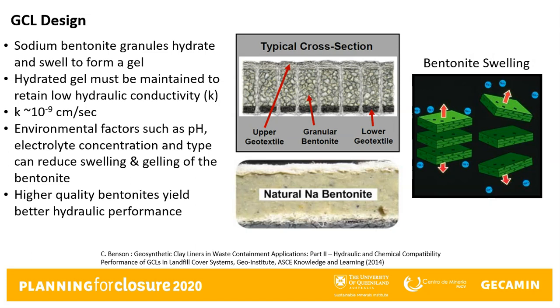In situations that involve higher electrolyte concentrations, the swelling potential of the bentonite can be significantly reduced, which can cause an increase in the hydraulic conductivity.